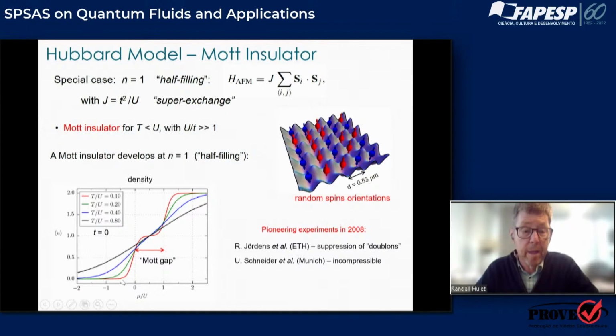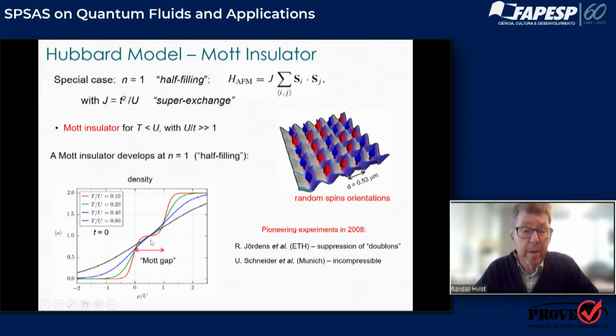At a chemical potential of 0, the Mott gap begins to develop. And when the chemical potential increases to 1 in units of the on-site interaction, it begins to grow again. And this flat region is called the Mott gap. It's an energy region that is as wide as the on-site interaction strength U. And once the atom gets inside this Mott gap, it very much becomes an insulating state.